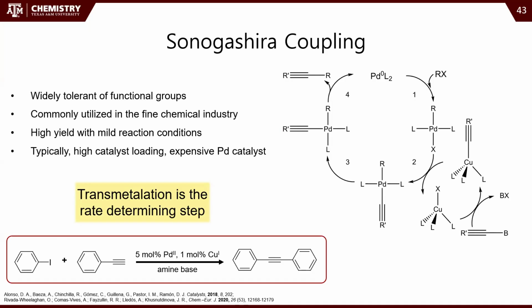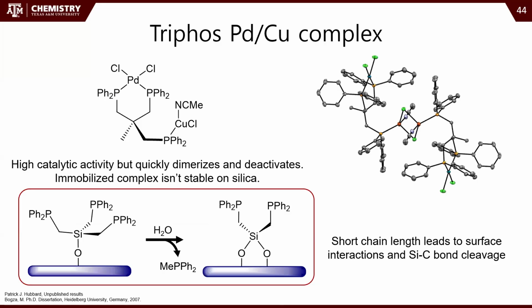So we're targeting doing this transmetallation step here. So there's a copper cycle and a palladium cycle, and you transmetallate to get that alkyne onto the palladium so that you can just reductively eliminate that off. And this is what's commonly believed to be the rate determining step. So we want to see if we can do that faster. And so we thought, okay, if we just put the palladium and the copper on the same molecule, then we don't have to wait for them to diffuse into each other. It might be able to just do the transmetallation intramolecularly.